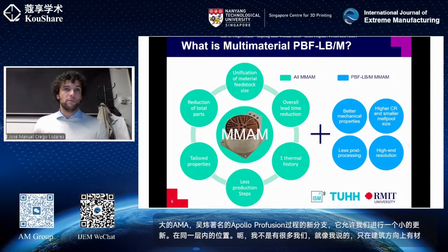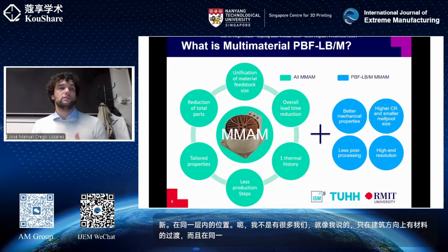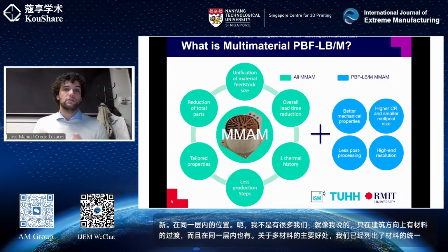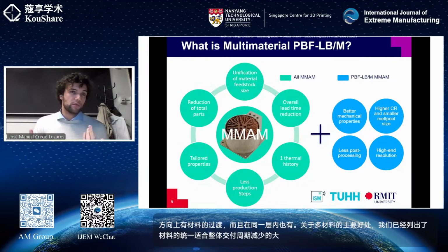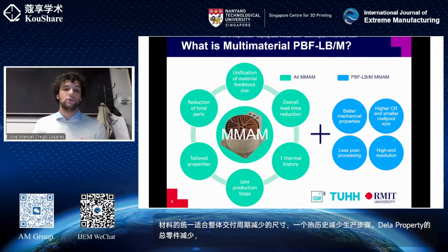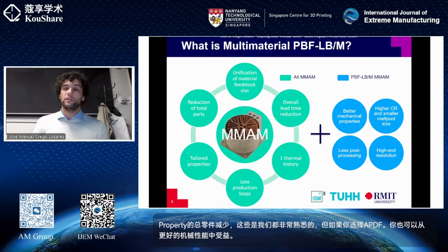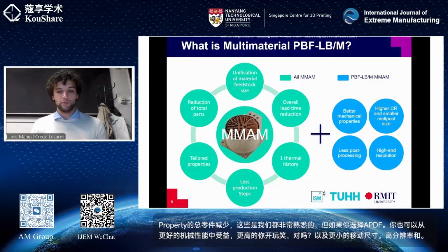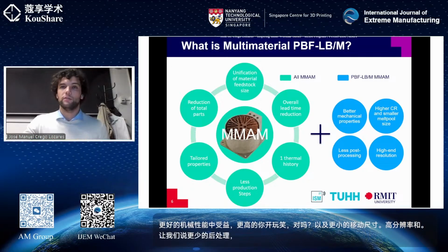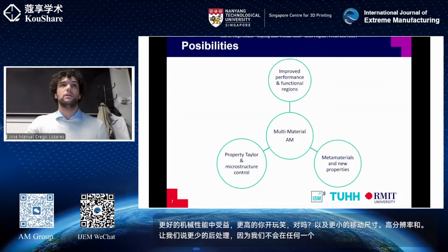Among the main benefits from multi-material, we've already listed the unification of material feedstock, overall lead time reduction, one thermal history, fewer production steps, tailored properties, reduction of total parts. These we are all very familiar with, but if you go for PBF, you can also benefit from better mechanical properties, a higher cooling rate, a smaller melt pool size that you can control, high-end resolution, and, let's say, less post-processing, because we are not going to get rid of it in any of the AM technologies, but definitely less.